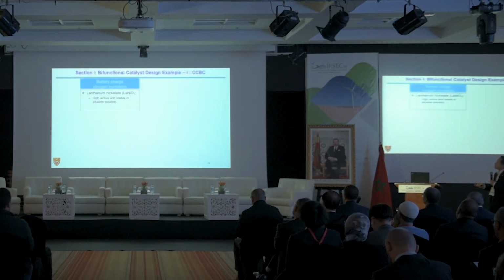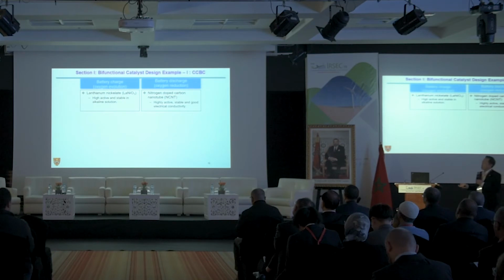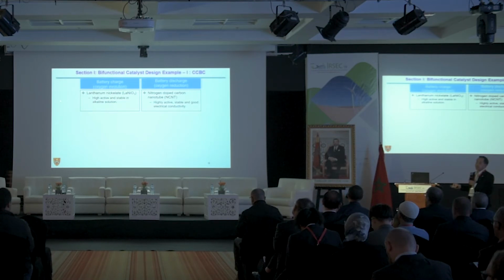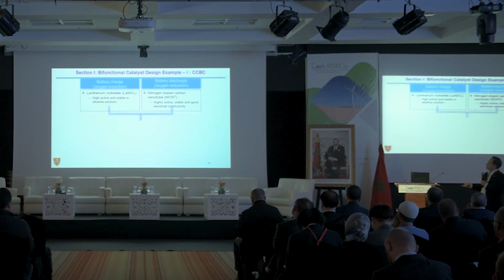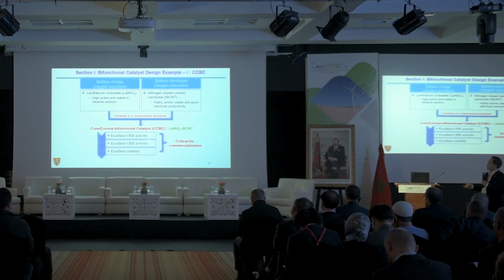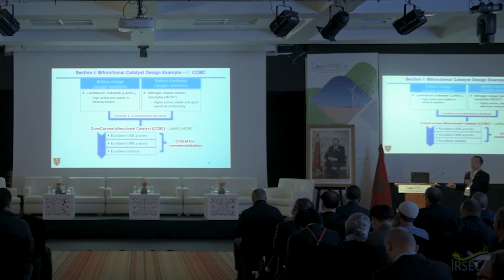So, for example, the first work we did is, because this is for a bifunctional catalyst, when we try to design, we try using lanthanum nickelate. This could be a good OER catalyst for the charging. And the nitrogen-doped carbon nanotube is proved to have good ORR activity, so it's suitable for discharge. So at the beginning in 2009, we tried to combine these two materials together so that we can have excellent OER activity, excellent ORR activity, and very good stability. And we are not just physically mixing. We try to synthesize together.